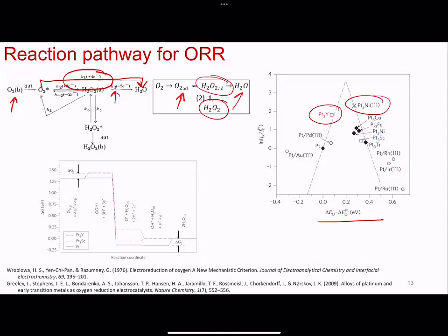So not a surprise, a 2014 Science paper comes out where 3 molar equivalents of platinum to 1 molar equivalent of nickel, exposing specifically the 111 facets in your nanostructure, will get you the highest performance while decreasing the price by a little bit, because now you replace some of the platinum with nickel, right? 25%. So that's what you do.